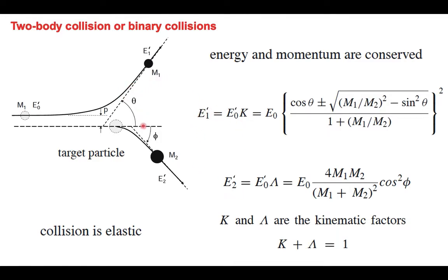Now remember that this deflection angle can be anything depending on the energy and the scattering cross section. So this can be deflected in any direction. This theta can even be 180 degrees, so it's actually reflecting back. That's called the backscattered ion. That is also possible, and we normally use this backscattered ion to characterize materials. Rutherford backscattering spectrometry is based on the ions that get backscattered by the atoms, and in that case, of course, the mass of these ions is very light, so normally helium is used.